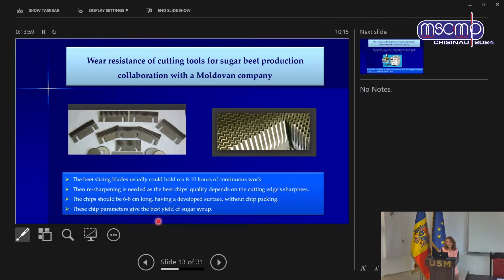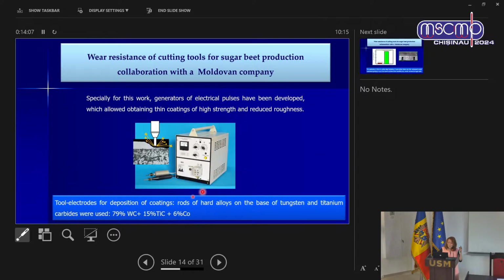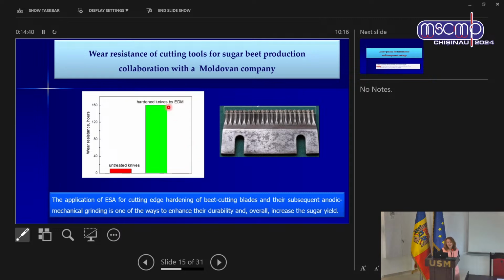In this case, in our lab, a generator of electrical pulses was specially developed for this application, which was able to deposit a coating with high strength and reduced roughness, and the composition you can see here. It's mainly tungsten and titanium carbides, which is of course a really hard material. And that's why in the end we obtained really nice results. For example, from 10 hours we were able to achieve 160 hours of work. So of course it was an economically convenient and practical result.